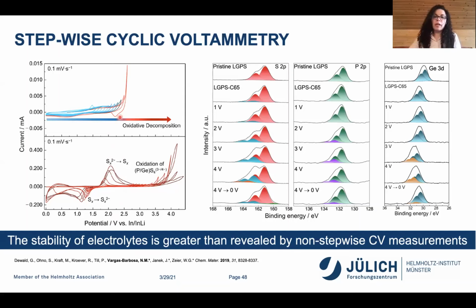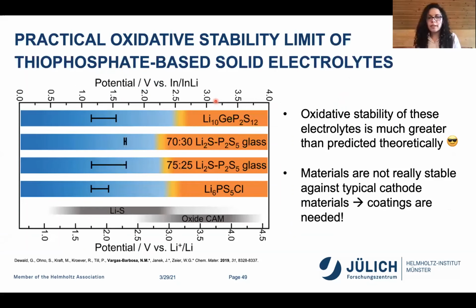We can simply say, okay, we're not going to push the material past its stability window. With that, we did it in various thiophosphate electrolytes, and we were able to establish these kinds of ranges for the thiophosphates. Most thiophosphates have a stability of about 3 volts versus lithium, even the crystalline ones, and also some of the amorphous, maybe a little bit less.